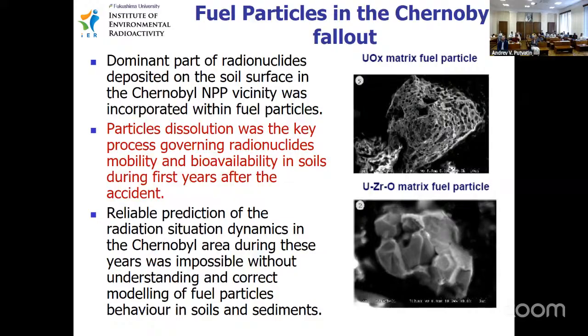However, outside the 30-kilometer zone, for example, in Western Europe, mostly condensation particles were deposited, which were much more soluble, and as a result, radionuclides in these particles were more bioavailable. Particle dissolution was the key process governing radionuclide mobility and bioavailability in soils during the first years after the accident.